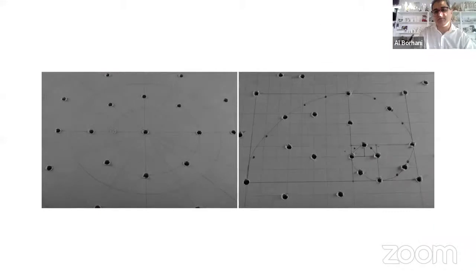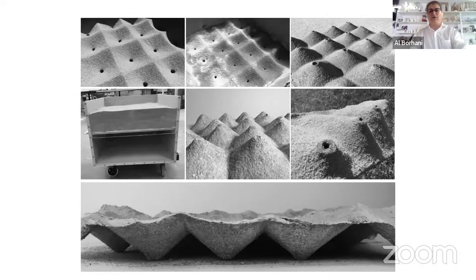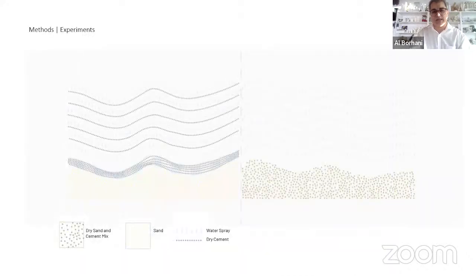And it was interesting, the journey from 2D to 3D, a very simple way of making a couple of holes on a board, and immediately you could jump to the excitement of 3D work. The process was about adding cement on the top layer of sand when some water was used to make the shell. Here we can see a simple diagram that shows maybe 2 different ways to make the shell. One way is to mix cement with sand in the beginning, and then go through formation.